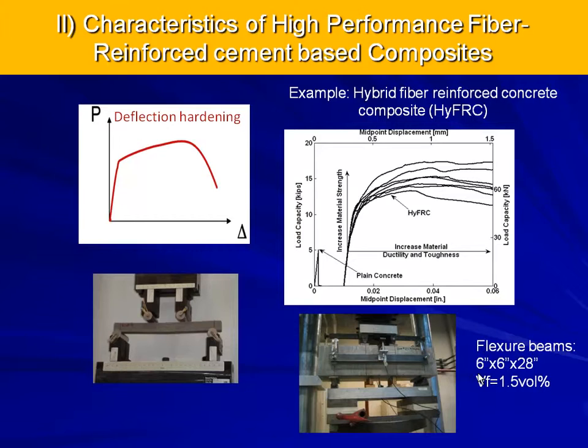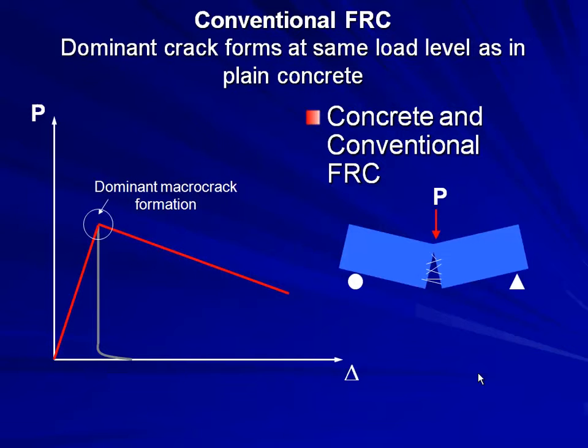Another example, or another, I should say, characteristic. Let me go one step further. I have one other slide, which I think makes it very clear why it's different from a conventional fiber-reinforced composite. If you look here, a conventional fiber-reinforced composite fractures at the same stress level or load level as the concrete. So you have some softening behavior right here, but the initiation of the dominant crack is at the same load level. So you can imagine what this does to your durability. It doesn't enhance it at all, because all the aggressive agents can come in as easily as before.